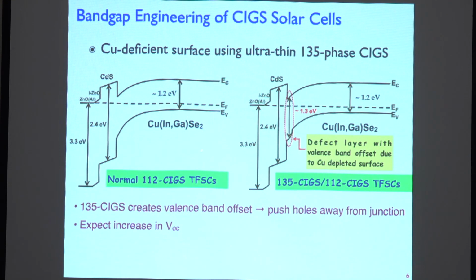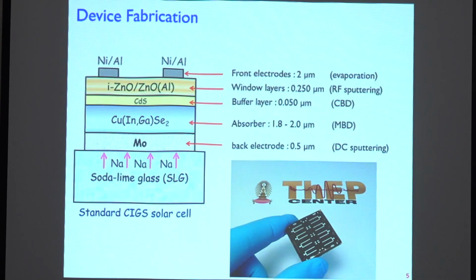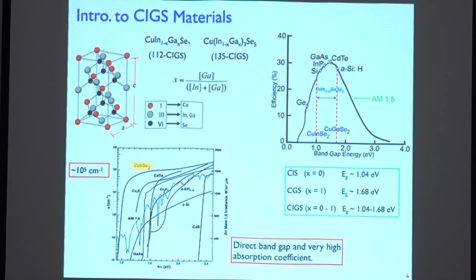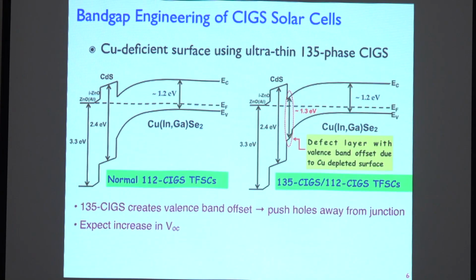The normal structure, the band diagram, I will not go into much detail. The 112 CIGS, I forgot to mention, has this molecular formula: 1 copper, 1 of group 3, and 2 of group 6. The 135 is 1 of copper, 3 of group 3, and 5 of selenium. And we have the normal structure of 112 looks like this. The band gap of this 112 CIGS that we fabricate in the lab is about 1.2. And it was found that the 135 CIGS was accidentally found on the surface of 112. And now in our research, we try to intentionally put a very thin layer of 135 on 112.